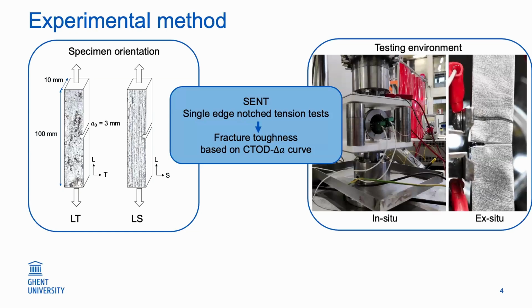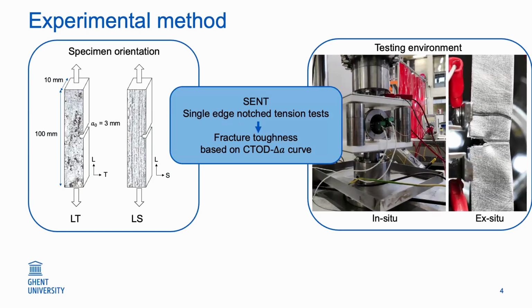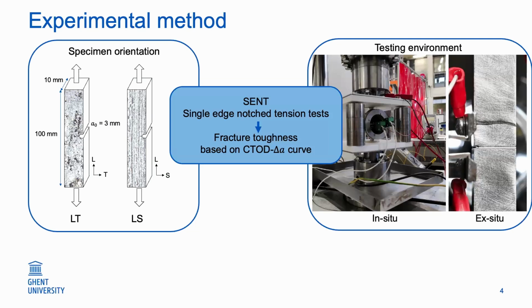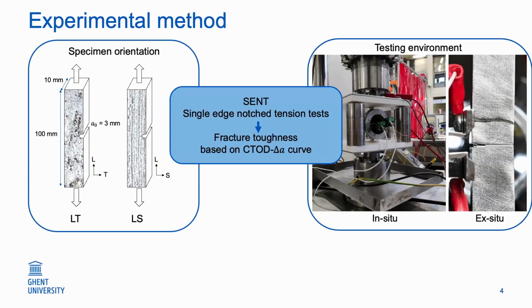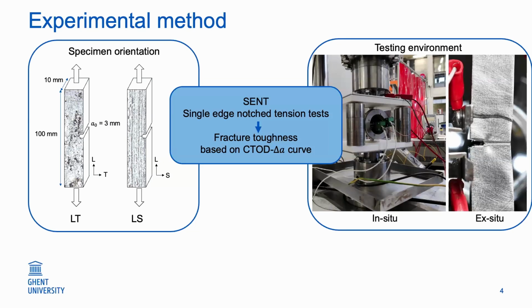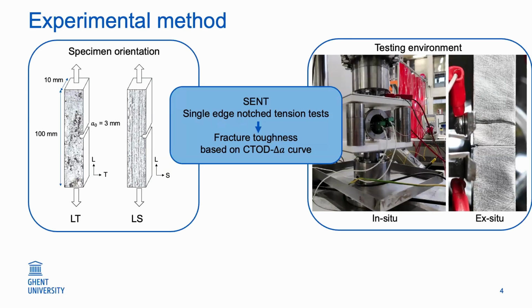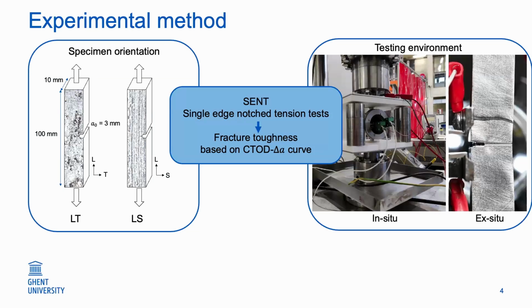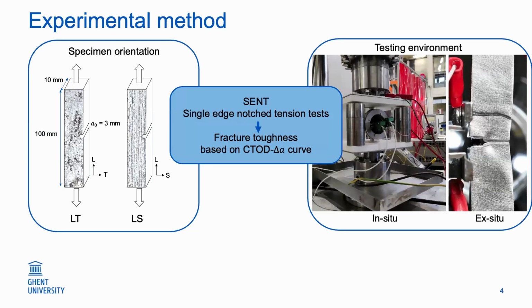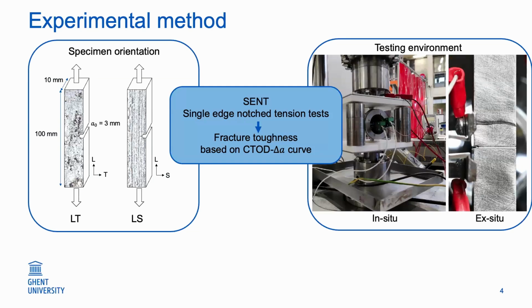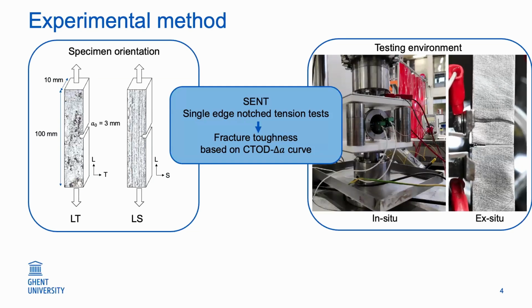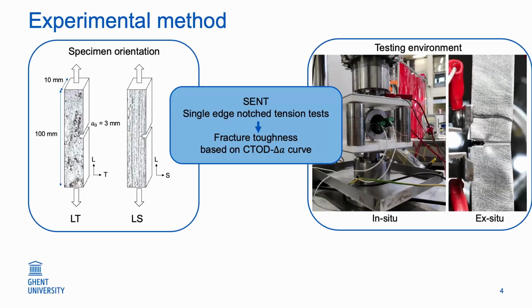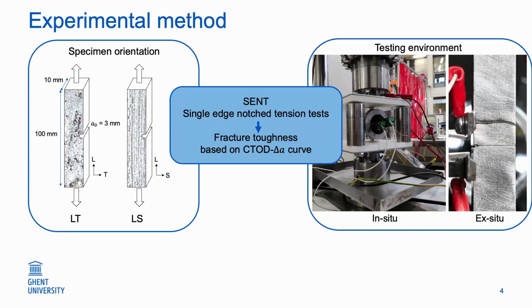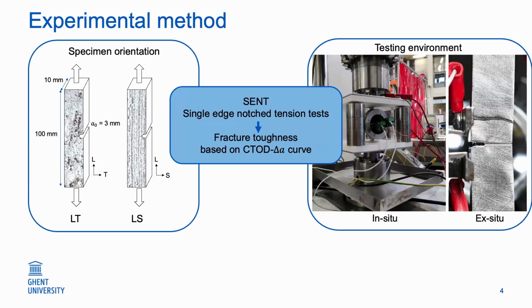And then on the right, you can see the two kinds of environments that I used. So we have an in situ cell we built for actually doing the toughness test with in situ electrochemical hydrogen charging, and of course just ex situ after pre-charging. For the resistance curve, we are monitoring CTOD with a double clip gauge method. You can see the clip gauges there on the in situ chamber, and also doing DCPD to monitor crack extension.